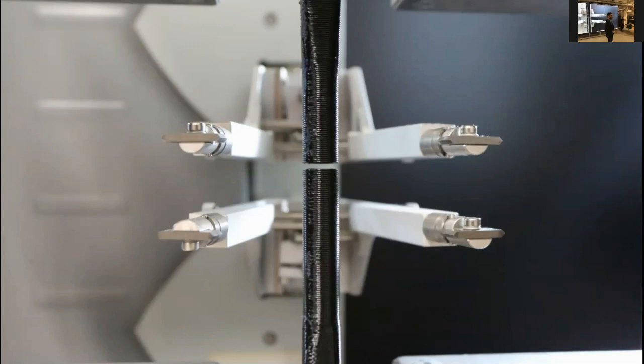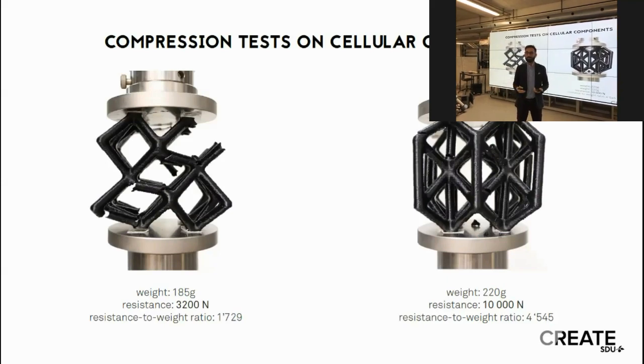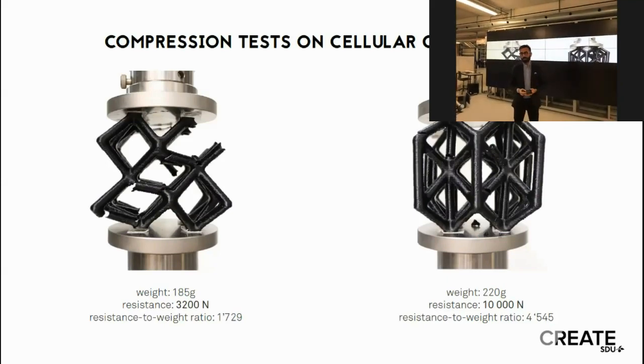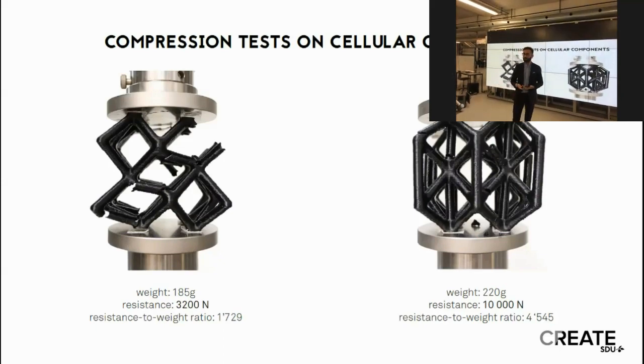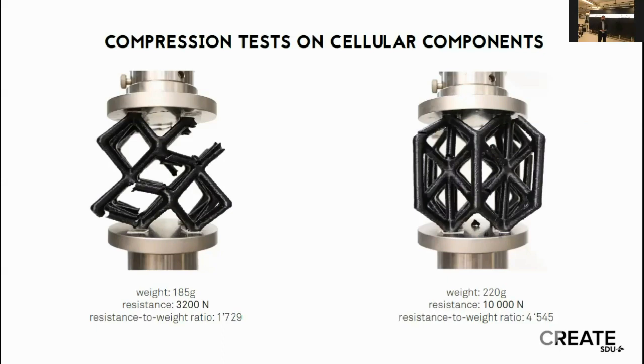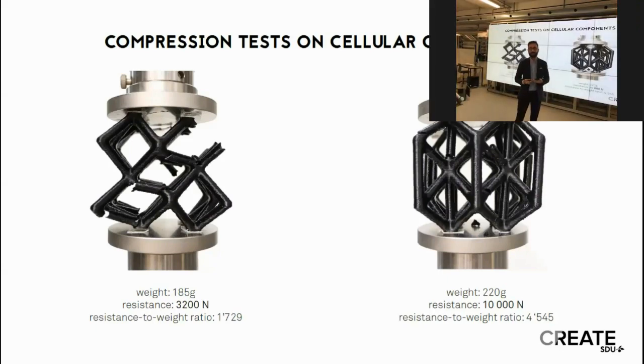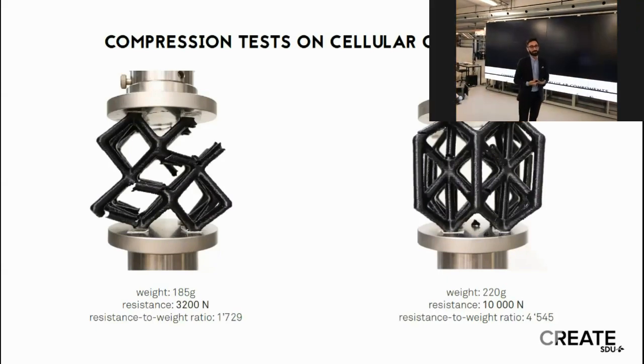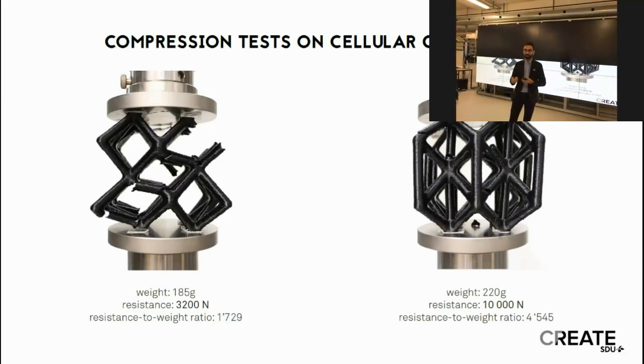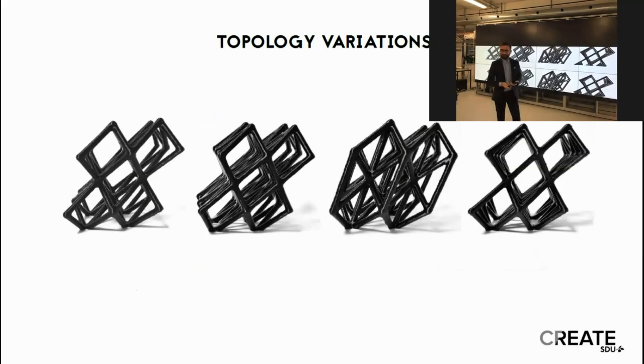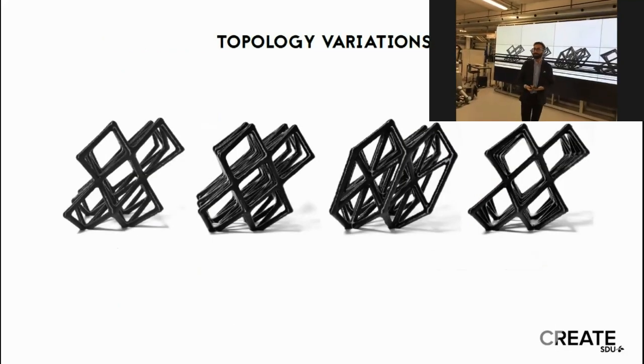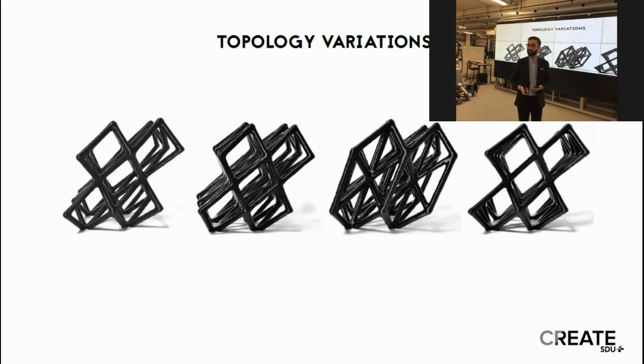We also started with material testing for 3D printing and biopolymers. Referring to this image, on the left side you can see an elastic lattice brick, which works in compression quite well. On the right side you see a rigid one, which has a different topology and can withstand up to 1 ton in compression, which is 4,500 times its own weight. That's very much for a small sample of plastic, 220 grams. This shows that you don't need the most impressive material, but you need to use material and geometry in a smart way. These are various experiments with different topological variations of this kind of lattice.